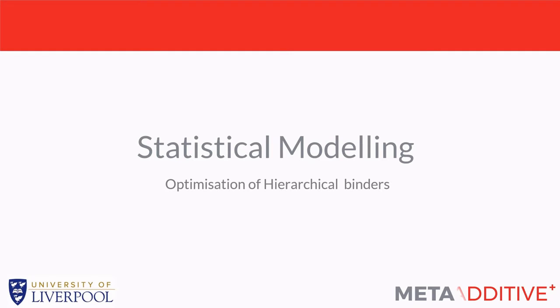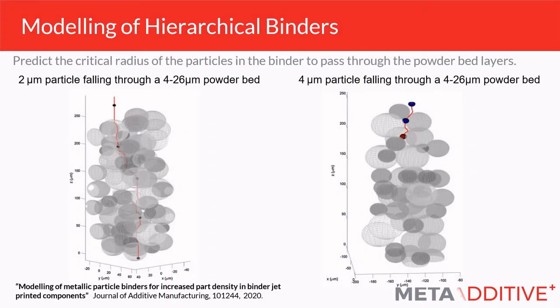But instead of doing lots of lengthy experiments that are time consuming, can we use some statistical modelling that might be able to optimise this process? And that's what we've been doing recently, and we have a paper that's just recently been published in the Journal of Additive Manufacturing. One of my postdocs has been using Monte Carlo simulations to model or predict the critical radius of the particles you need in your binder to be able to pass through the powder bed.